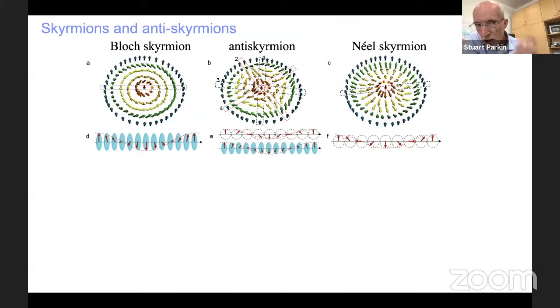Now, what was interesting, theoretically, it was predicted that certain types of magnetic systems with strong Dzyaloshinskii-Moriya exchange, with a certain symmetry, a more complicated symmetry, would show a ground state that could consist not of a Bloch or Néel skyrmion, but an antiskyrmion. And an antiskyrmion is more complicated, as shown in this cartoon. As you go around the periphery of this circular device, the walls change from a Néel type wall to a Bloch type wall, back to a Néel type and a Bloch type. And each time the wall type varies, the chirality, whether it's clockwise or anti-clockwise, also changes. So it has a much more complicated structure, which is determined by the symmetry of this exchange interaction.